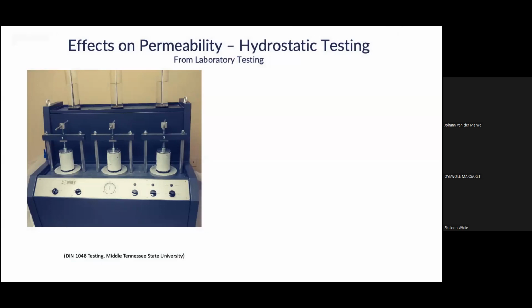So, just some quick examples. This was some testing done at Middle Tennessee State University. You have concrete specimens that were made out of the same wheelbarrow, some treated and some not. This is the DIN 1048, now called the EN 12390-8 test, where water is applied at 5 bar to the concrete. This test used a particularly bad concrete, I think a water to binder ratio of around 0.6, poorly graded aggregate, et cetera.